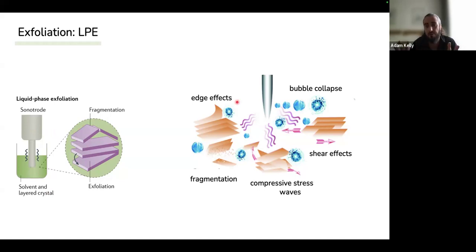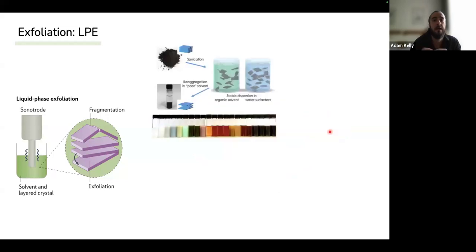So you get all this transfer of energy from the tip. But this causes exfoliation and fragmentation via edge effects with interactions. We get fragmentation of our nanosheets, breaking them up. There is stress transfer then from the formation of bubbles and the collapse of those through cavitation. This transfers stress to the nanosheets, breaking up the crystal, and then they shear apart as well. So this is a very mechanically aggressive method for just breaking apart the crystal into monolayers.